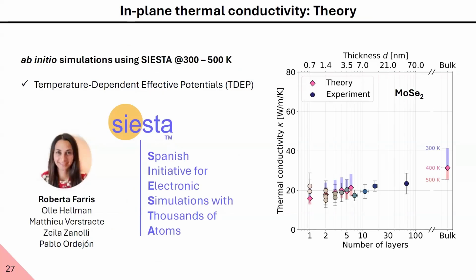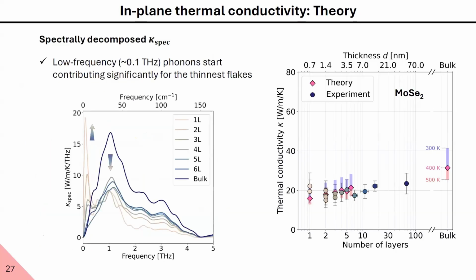So, to understand our results, we asked our collaborator Roberta to perform ab initio simulations using the Siesta package, and we see that our experimental results agree very well with the calculated thermal conductivity. But importantly, we understood that things were actually changing. For thick materials, the main contribution to the thermal conductivity comes from modes centered around 1 terahertz. If we decrease the thickness, we have the contribution from these phonons decreasing, and the appearance of lower frequency phonons for the mono and bilayer samples. These low frequency phonons have in turn very long mean free path, and therefore they travel very far away before they start scattering.